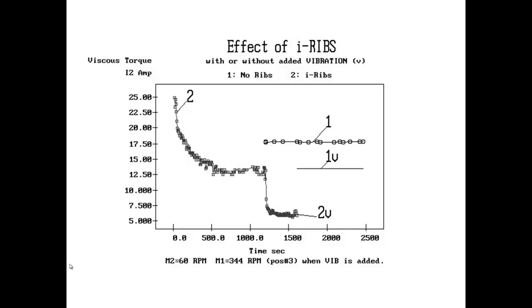Of course, there is even more to say, but I'm not going to describe this in this presentation. If I combine the external vibrator 2V, which is a curve with the ribs included, I still increase even further the reduction of viscosity. So now I have reached a level of approximately 6 amps, compared to a value which was 25 at the beginning before rotating the melt.